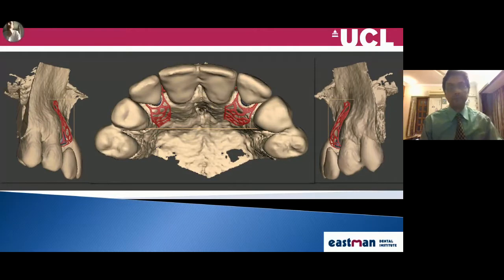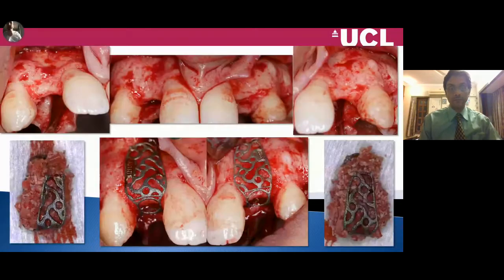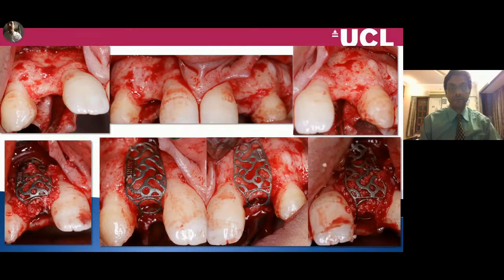You can see the design of the 3D titanium meshes there for the upper right 2 and the upper left 2. And these are the intraoperative pictures, very similar to before. When they opened up the surgical area, there was a large horizontal defect on both the upper right 2 and the upper left 2 area. We use a combination of Bio-Oss and autogenous bone harvested from the same area that we're doing surgery, so we don't need to go anywhere else in the mouth. We put that within our titanium mesh, then we adapt our titanium mesh to the space, and we just have to secure that with some screws at the apical aspect, both buccally and palatally. You can see the screw here on the apical aspect of the titanium mesh with the screw hole that was already incorporated into the design.